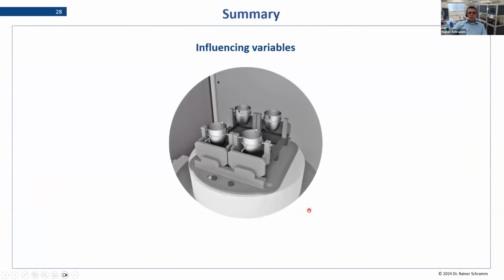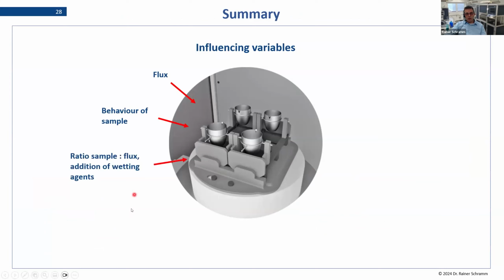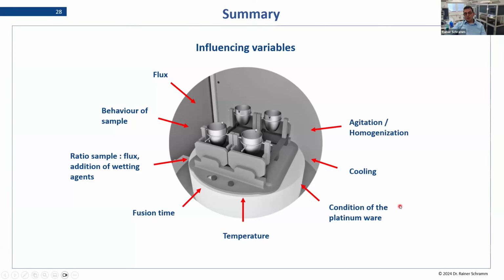So let's summarize this. What are our parameters we have to get under control? It's the flux, of course. It is the behavior of the sample. So how much glass forming it has itself, how much surface reducing elements it has inside. It's the ratio between sample flux, and do we need to add non-wetting agents? Fusion time is important, the temperature, which is of course also a function of viscosity, condition of platinum ware, how do we cool, and then of course also the agitation, homogenization process, is this really good enough?